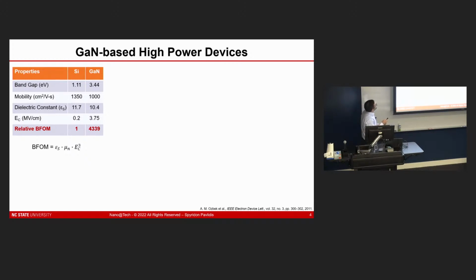If you skip to the second to last row of this table, you can see a clear relationship between the bandgap and the critical electric field. That is the main property that we are really trying to leverage as we scale these devices and try to make them more efficient. One of the figures of merit that a lot of people cite when discussing wide bandgap semiconductors is the Baliga figure of merit. You can see a very important cubic dependence on critical electric field. So once you have a couple factors of improvement in critical electric field, that very quickly translates to a blown up reason to go after gallium nitride.